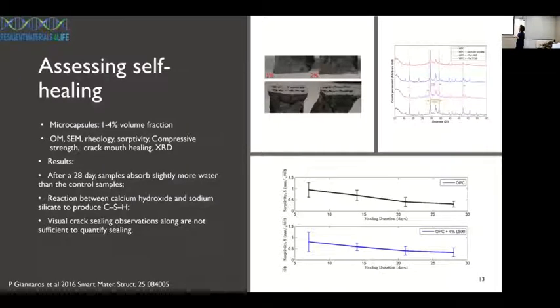Another interesting detail to discuss here is that when we are talking about sodium silicate for promoting self-healing, we are expecting that the CSH would be produced in the matrix. That's the reaction that we were relying on. And even though the crack mouth healing wasn't the best compared with the literature, where we have papers of capsules being capable of healing up to 1 millimeter of crack mouth, we observe a very good recovery in the transport properties after adding these capsules. That means that even though not all the healing products were deposited in the crack mouth, when we think about the crack being like a tip, some of the healing products would be deposited at the end of that tip, isn't it? So we are going to have the recovery in the transport properties, even though the crack mouth healing wasn't 100%.